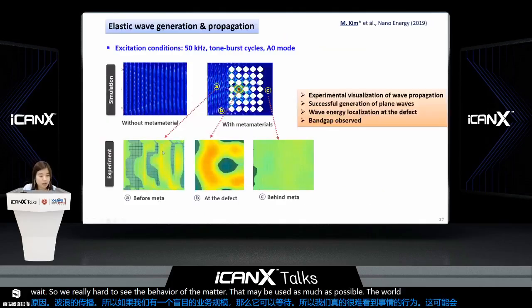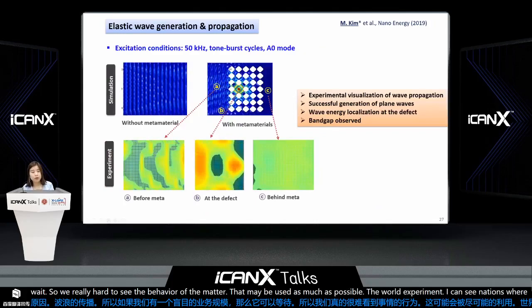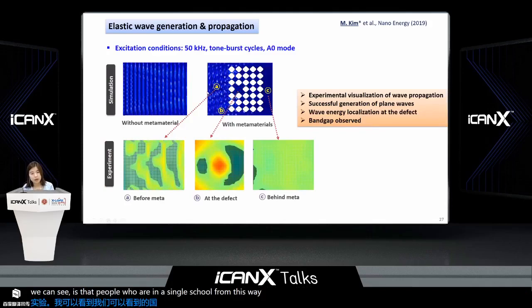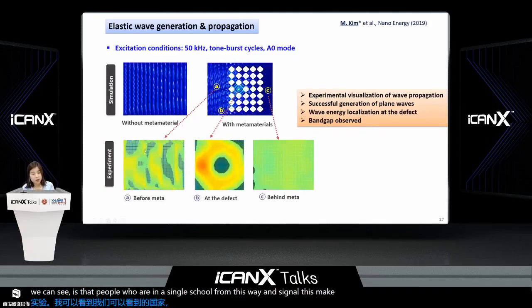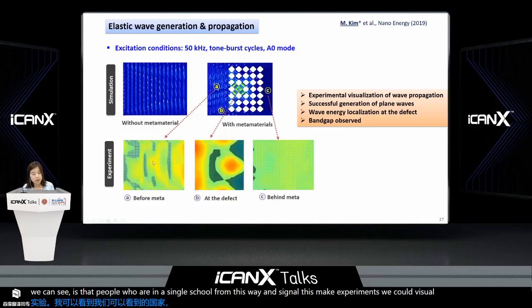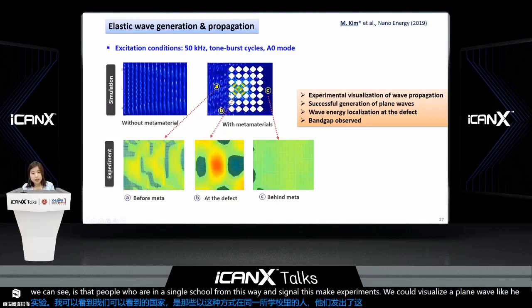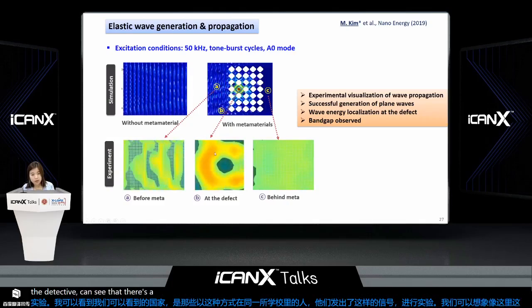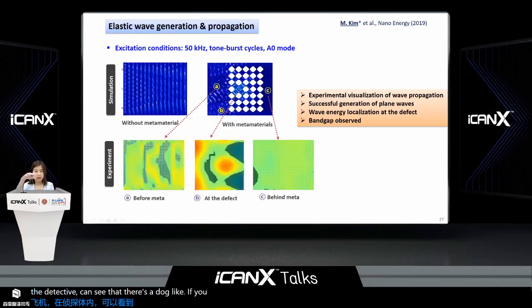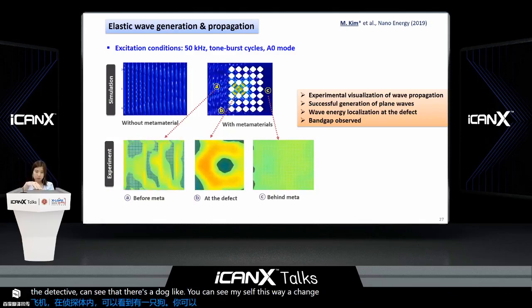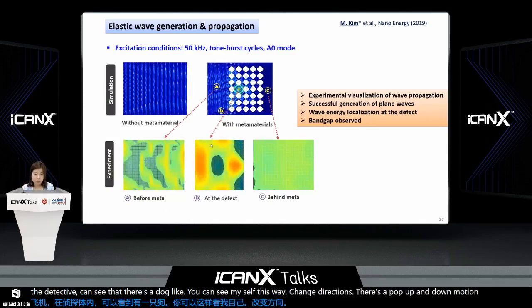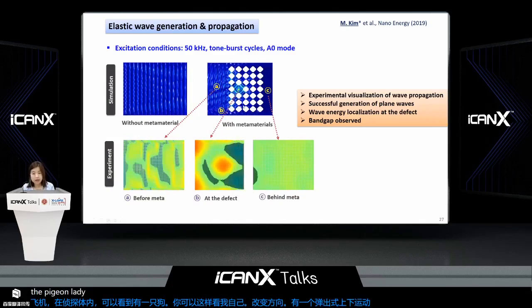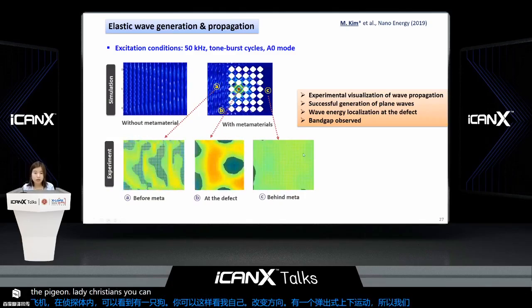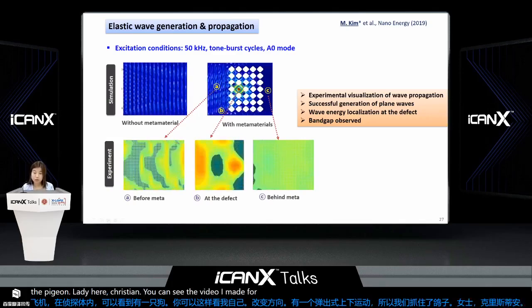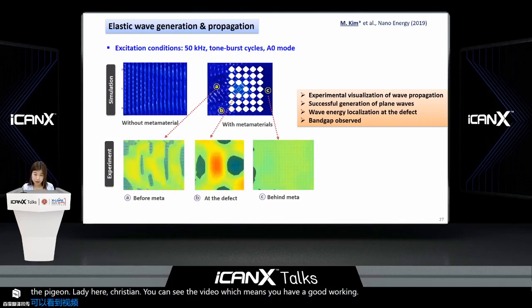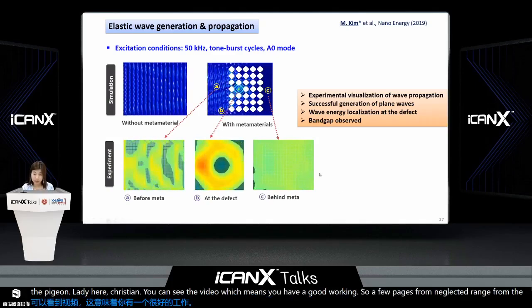So from the experiment, like in simulations, signals go this way, and experimentally, we could visualize the in-plane wave generation like here, beautifully. And inside the defect, you can see that there's a donut-like energy localization. So in the Z direction, there are up and down motions. So we attached the piezoelectric energy harvester later here. And behind the phononic crystals, you can see that there's little wave propagation, which means the band gap is working. A few of the waves are reflected waves from the boundaries I already mentioned.